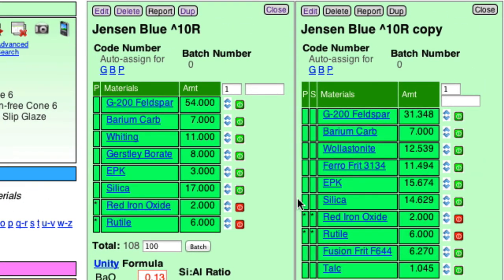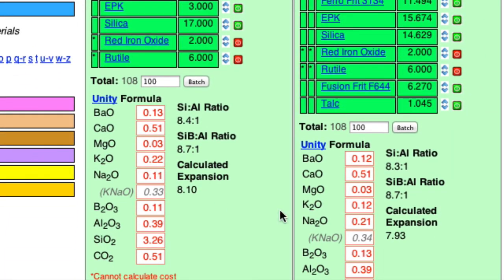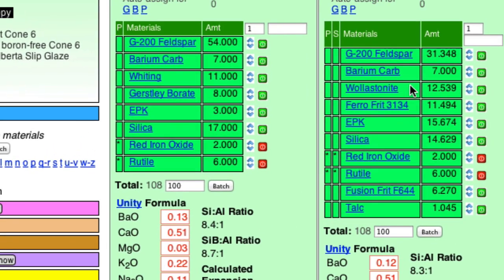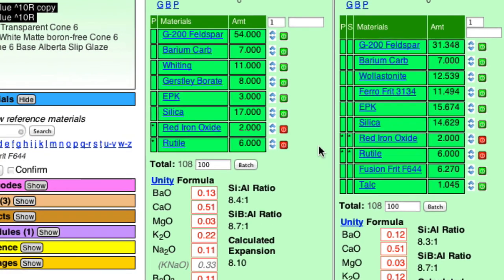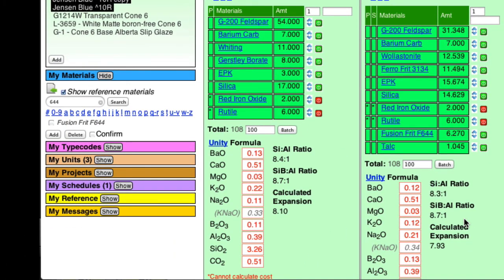So these, the chemistry of these two glazes is very, very similar, practically the same. Our new recipe is more complicated. We have more materials. But there are ways in the next stage to simplify this and at the same time resolve the crazing and the possible leaching. But anyway, the new glaze should pinhole and blister much less. It should dust less. It should suspend better as a slurry and it should apply better to the ware. And now tell me, how would you do all of this without ceramic chemistry?